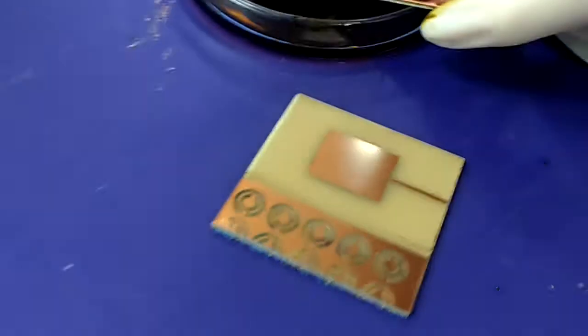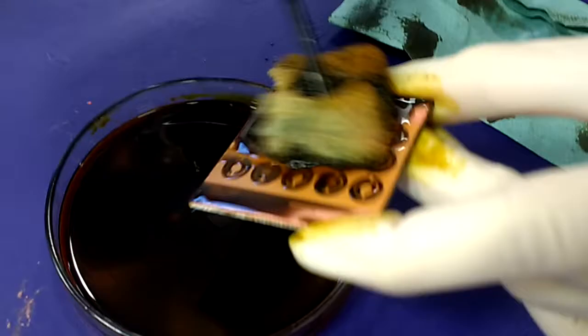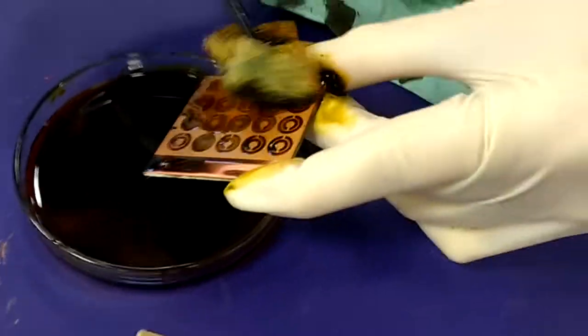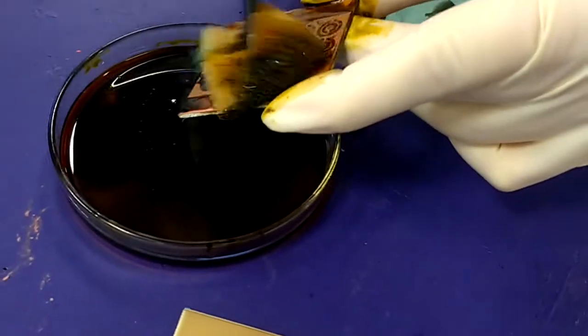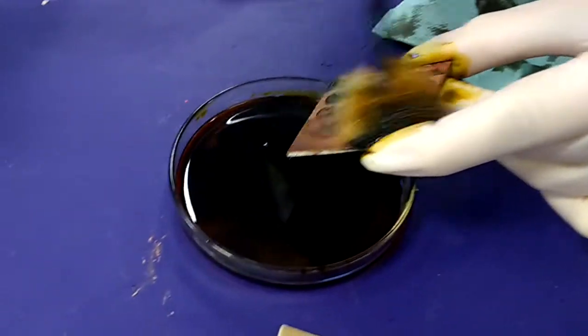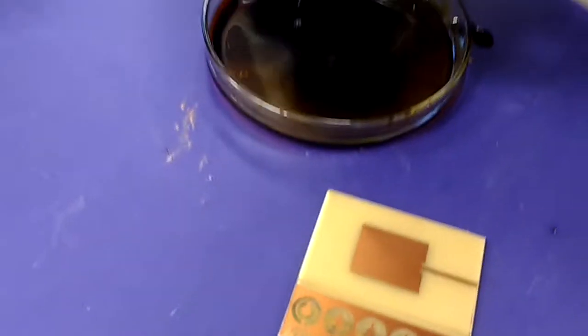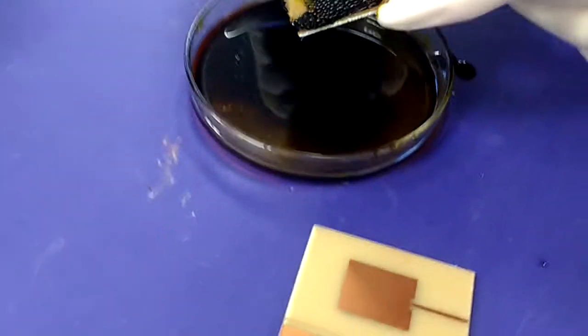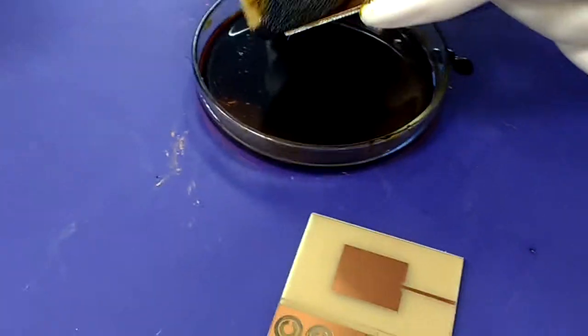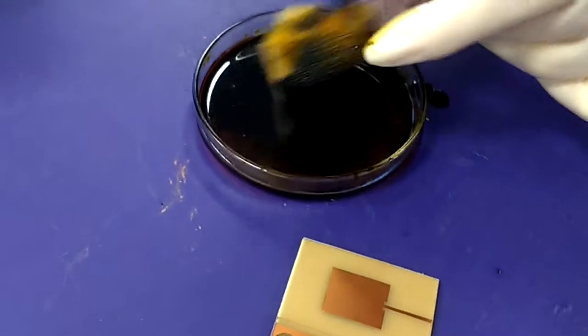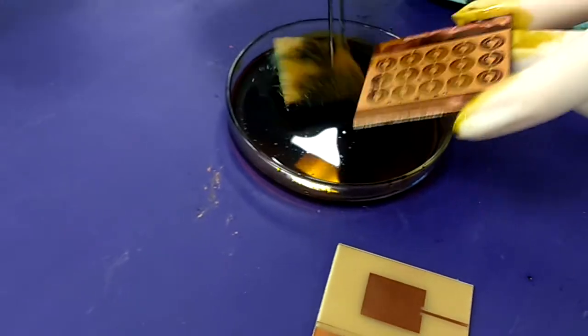We need to achieve that to fully expose it. The danger of this is that you might have put this into the light box for too long. Which means, if we do use ferric chloride for too long, we might over etch. This is something we have to be careful, especially if you have very thin width of the copper.